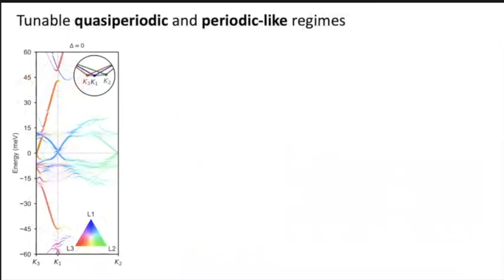So you cannot calculate the band structure, but you can calculate the spectral function for this type of quasi-periodic system. In a trace that goes from K3 to K1 to K2, where these are the K points of each of the layers, you can calculate how many states are present at each momentum at a given energy. The color scale tells you whether they're mostly on layer 1, layer 2, or layer 3, or hybridized in between. And what you can see is that there is a region near zero Fermi energy where the electron seems to see three layer-polarized Dirac cones, and they almost look like a periodic band structure would look.